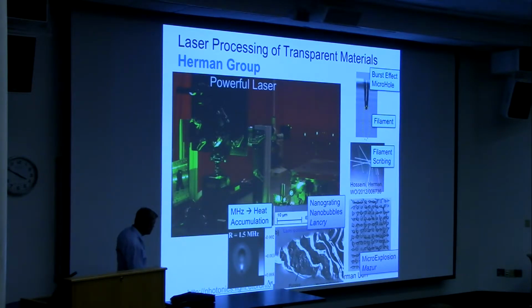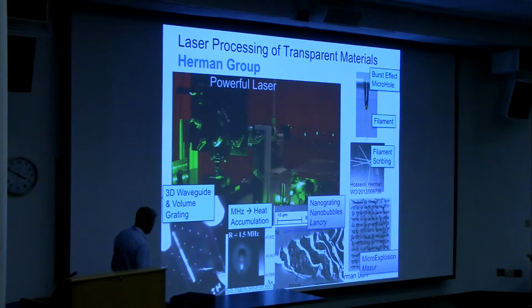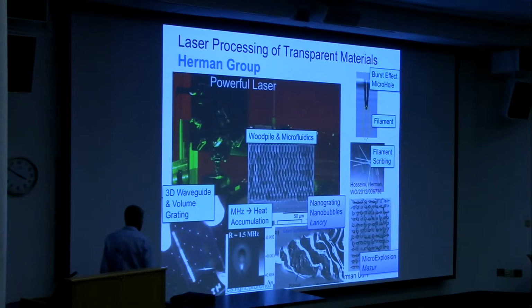This is an end view of a laser scan where you have a nice, fairly smooth positive index change here, and the symmetry of this is sufficient to make pretty low loss waveguides, for example. Ivan Zhang in my group discovered serendipitously again that if you modulated this while scanning, you could make gratings in here at the half wavelength periods. And so Bragg grating waveguides were formed simultaneously with the waveguides in that approach.